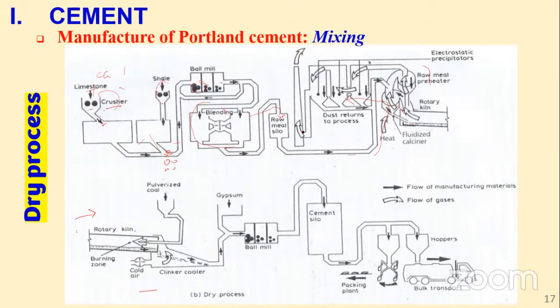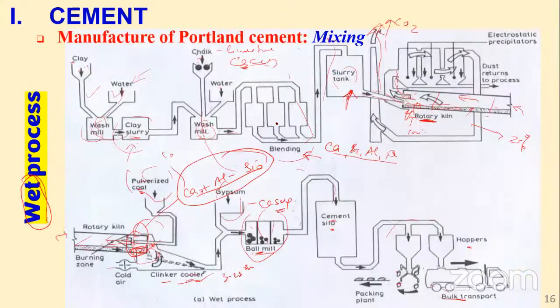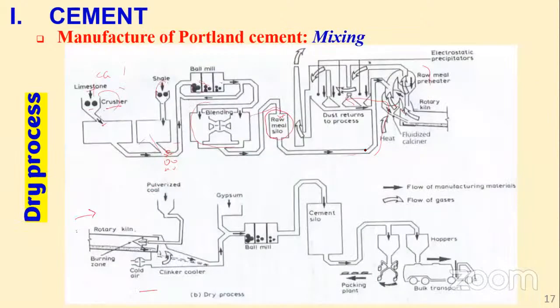Now, something that I should mention is that when we have these materials together and they are separate, like the way we had in our previous slide, we had slurry here. These ingredients are in different composition. So before we heat them so that they can fuse, we sample. Okay, there is quality control that is done. So samples are taken to measure the different composition of either of these. And if one is in minimal quantity, then they might be adjusted accordingly. So in a similar manner, the raw mix that we get here, we sample and then we check to see the composition. Depending on the type of cement that we want to produce, then we can adjust the composition, okay?